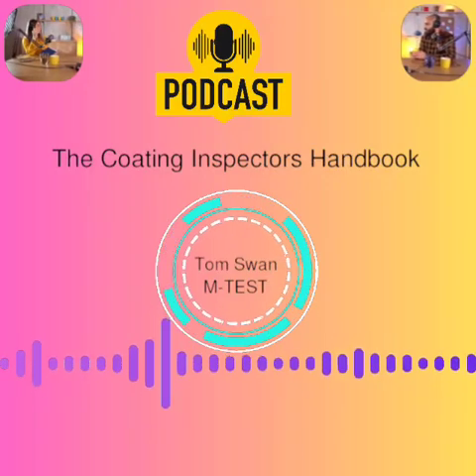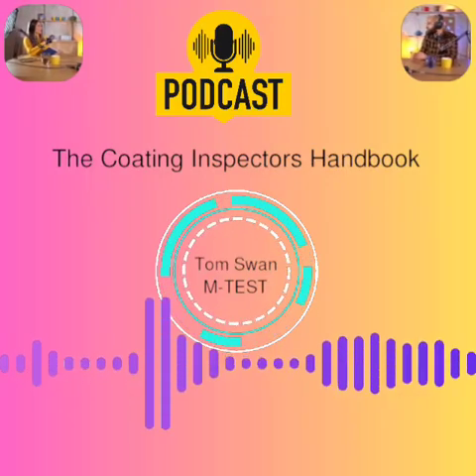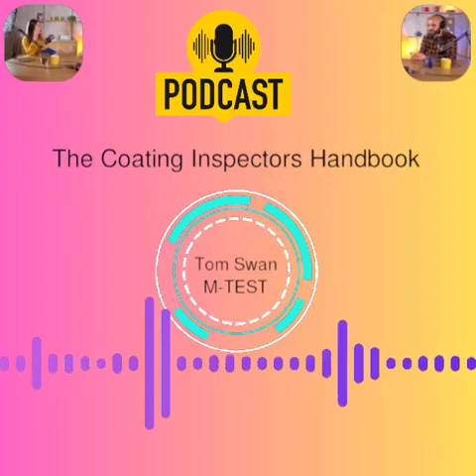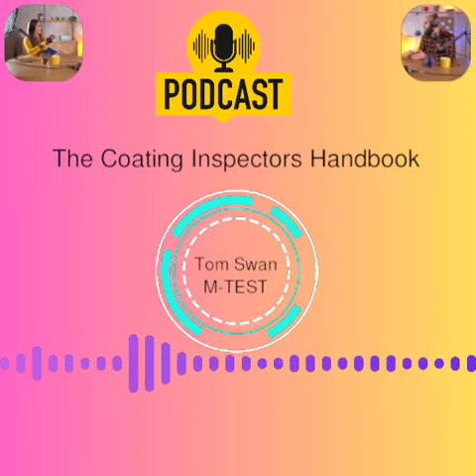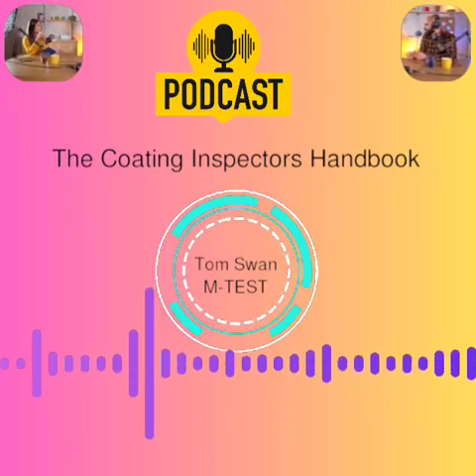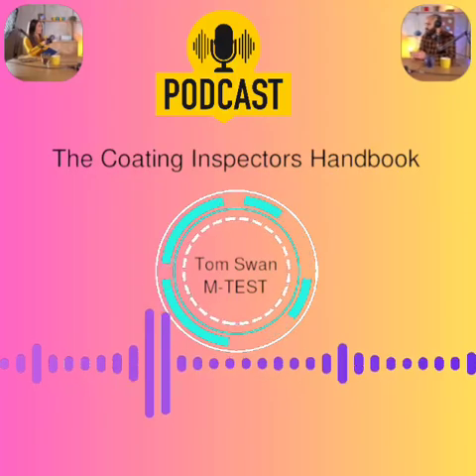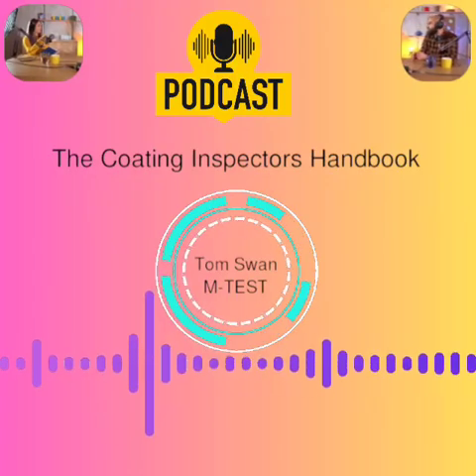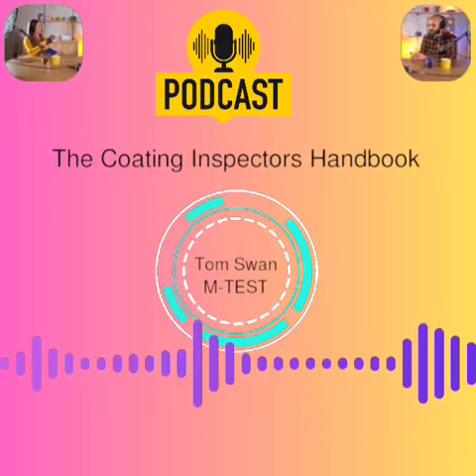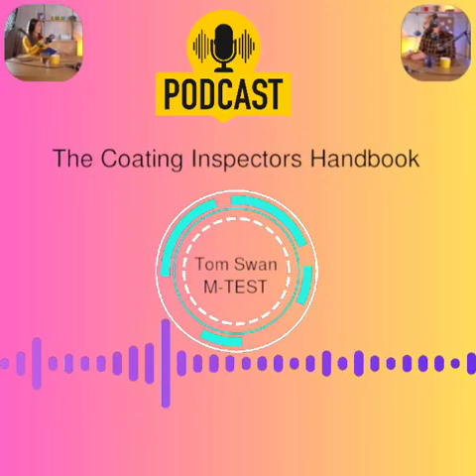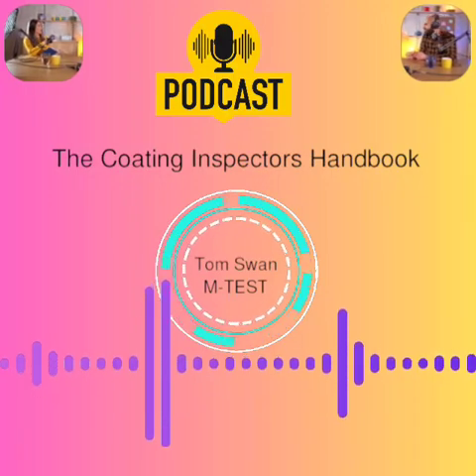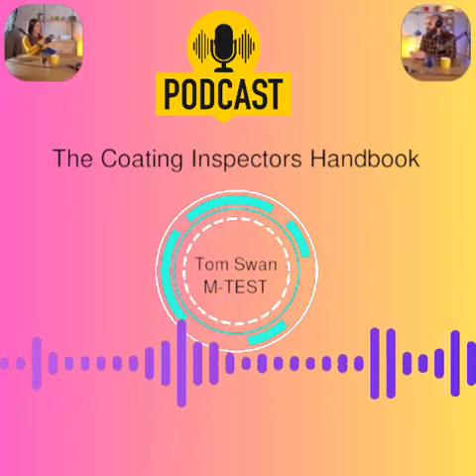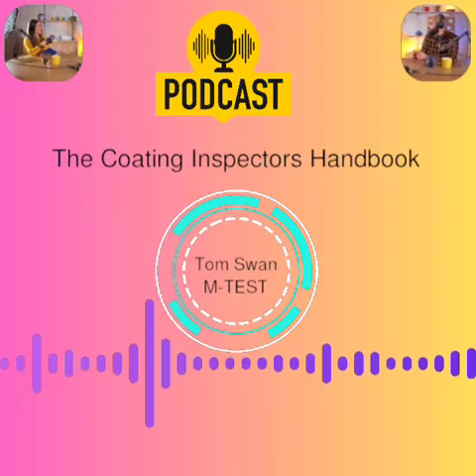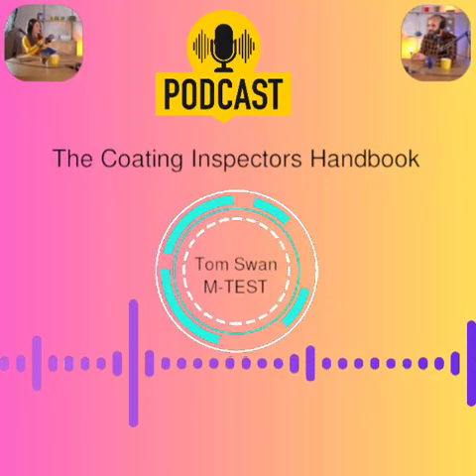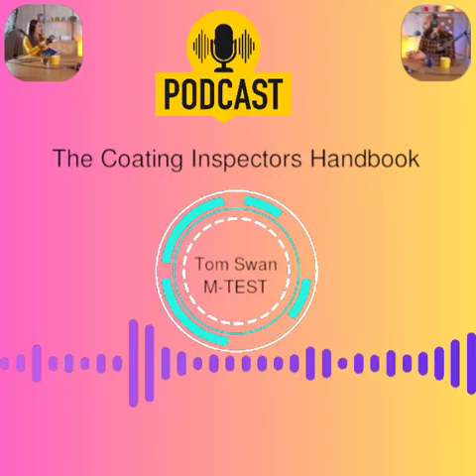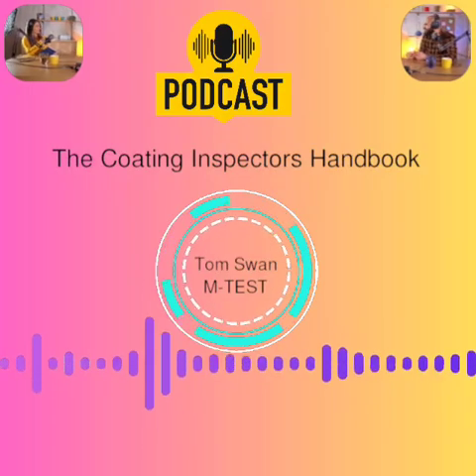Can you use high voltage on thin films? Under 20 mils? You can, but the risk of damage is higher. NACE RP0188 gives suggested lower voltages, like 1500 V for 8 to 11 mils. Use with caution. High voltage procedure on metal: know your DFT first. Set the voltage correctly: spec, PDS, 100 V per mil, or the NACE formula. Ground the tester firmly to the bare substrate. Pass the electrode brush or spring over the surface systematically. The spark jumps at a holiday and the alarm sounds. Lots of standards cover the details.